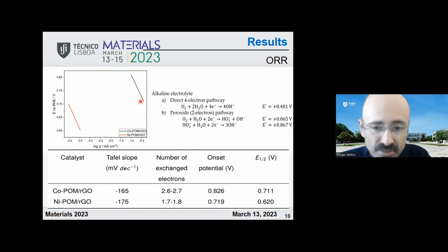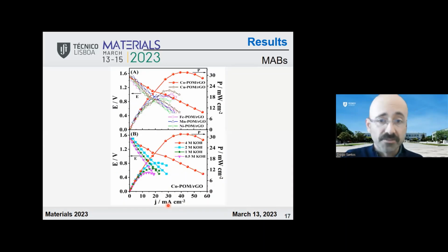So these are the reactions involved in oxygen reduction reaction, which is also a 4-electron reduction. And we see here the Tafel slopes that we measured, with cobalt POM being better with a slightly lower Tafel slope. The number of exchange electrons here was closer to 3, and here was around 2. So meaning we are not being able to get the 4-electron reduction reaction, which is the aim, but still it was very good. Then to finalize, we built the metal air batteries, and the results with the metal air batteries were very interesting, specifically with the one where we use this cobalt POM.